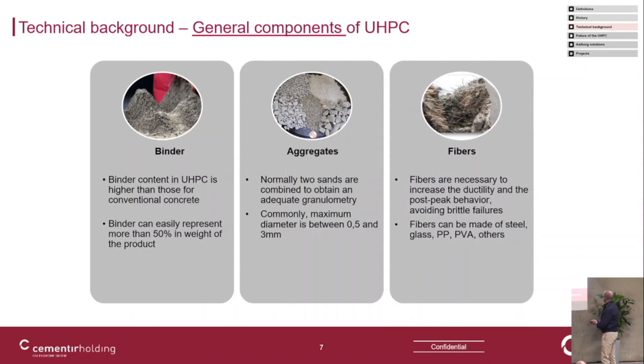Then, to make the UHPC, you also need the fibers to have the flexural strength. In our approach, that's maybe a bit different than other similar products. We leave the choice to the customer of which type of fibers you can add, and also the dosage. For structural applications we apply steel fibers, or you can also choose stainless steel fibers. For decorative applications, you have more the PP fibers, polypropylene, or PVA, or even glass fibers.